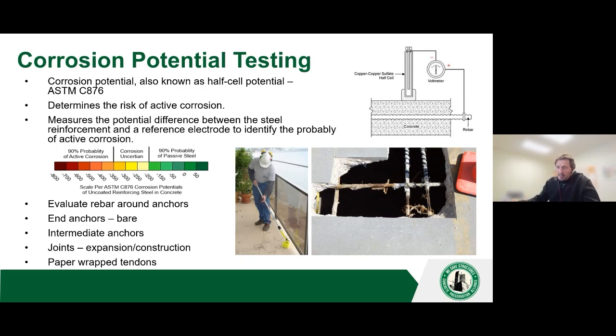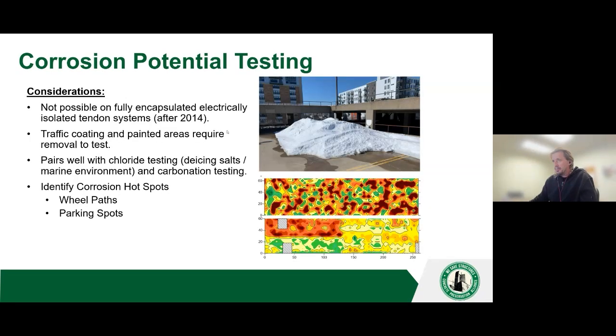If things aren't epoxy coated or not encapsulated in a plastic, if bare end anchors, intermediate anchors, this is a great way to say, okay, we've got a construction joint with some intermediate anchors, but we don't know what's going on. We're not seeing a lot of evidence of something going on, but we want to check it nonetheless. Maybe water's getting deep down into a beam or a slab or whatever. We can do this test to see if there's active corrosion going on in those areas. And of course, around expansion joints, and then, like I mentioned, paper wrapped tendons.